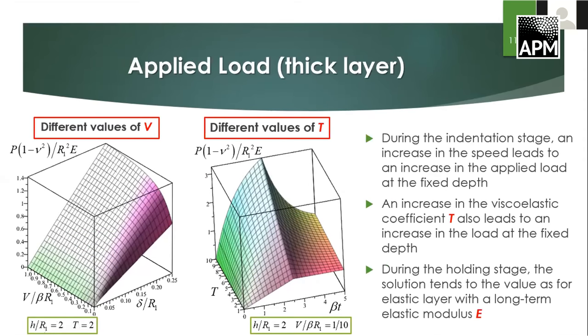This slide presents the study of the applied load dependence on time for different values of the indentation speed v, and for different values of the viscoelastic coefficient t. As follows from the first graph, an increase in speed leads to an increase in the applied load at a fixed depth, only during the loading stage. An increase in the viscoelastic coefficient t also leads to the same results. During the holding stage, the solution tends to the value corresponding to the elastic layer with the long-term elastic modulus E.